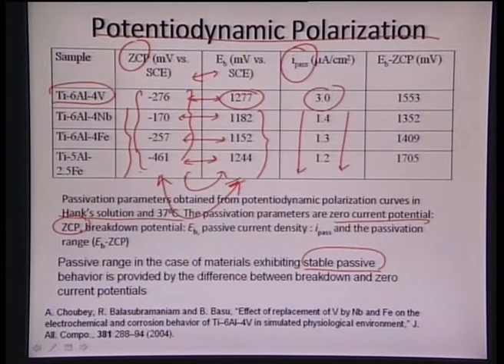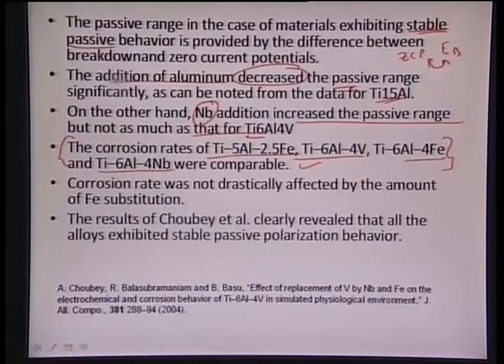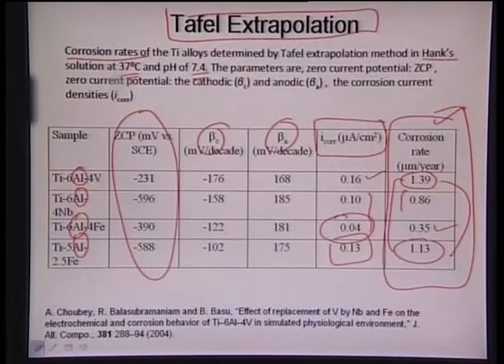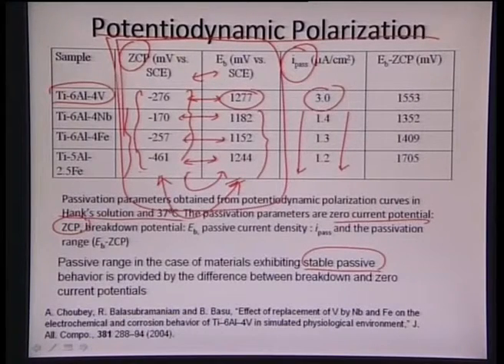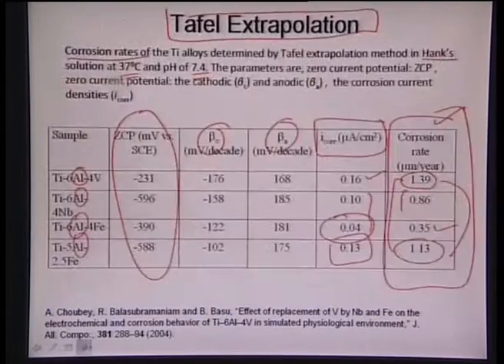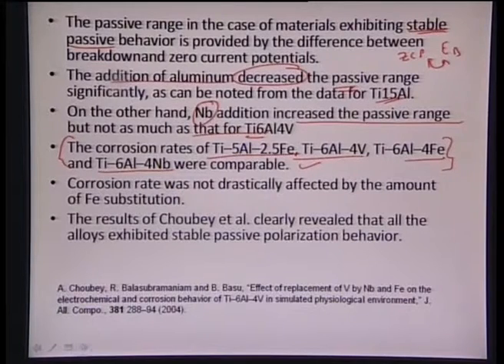Like all these are showing a much more vast passivation regime out here. So that is the role of aluminum: aluminum is deteriorating the passive regime, whereas niobium tends to increase the passivation regime, as we can see in this previous case, that once we start adding the niobium out here, we can see much more difference between the two regimes. So overall, we see that the corrosion rates are not so different for all these materials, even when we are adding certain iron to it, and they also clearly reveal that the stable passive polarization behavior exists between zero corrosion potential as well as the breakdown potential.